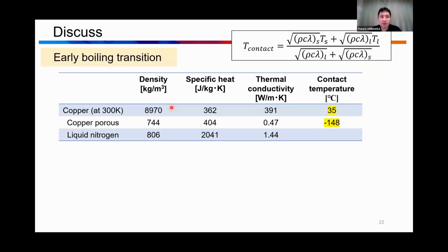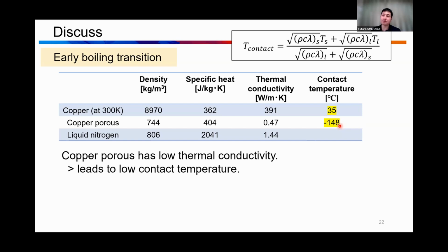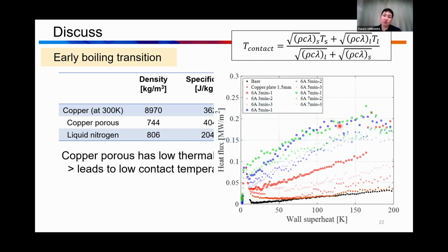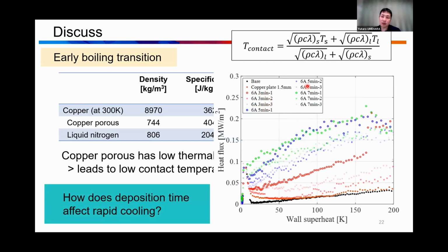So we try to understand the mechanism of this rapid cooling when we use copper porous. This one shows the properties of the copper, the copper porous and the liquid nitrogen. Based on these properties, we calculated the contact temperature. In the copper case, the contact temperature is 35 at the initial temperature. But when we use copper porous, the contact temperature is very low. So this low contact temperature may have some effect on the rapid cooling. But when we use different deposition times, 3 minutes and 5 minutes, the cooling time changes a little bit, because the heat flux is a little bit enhanced.